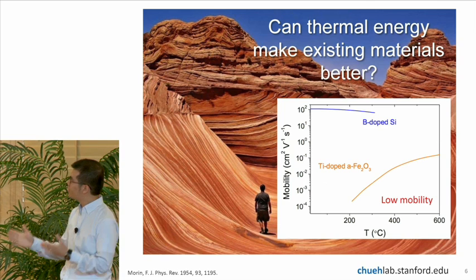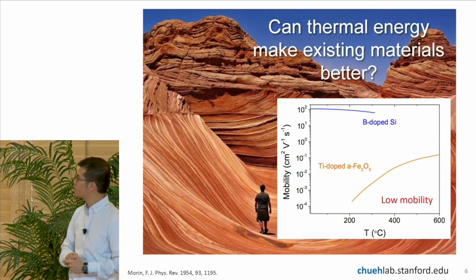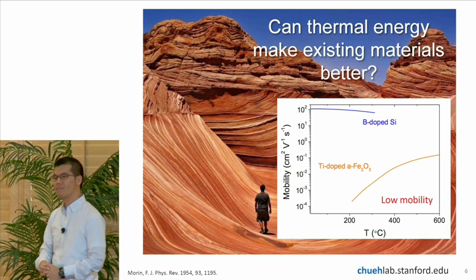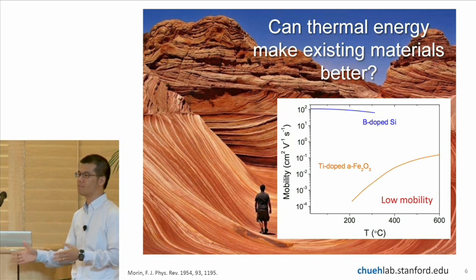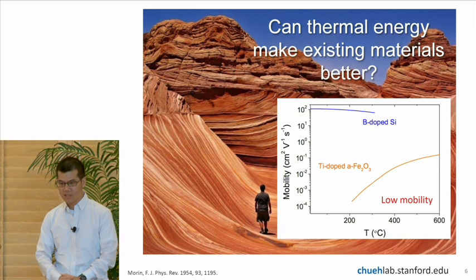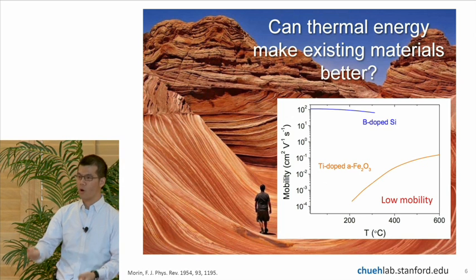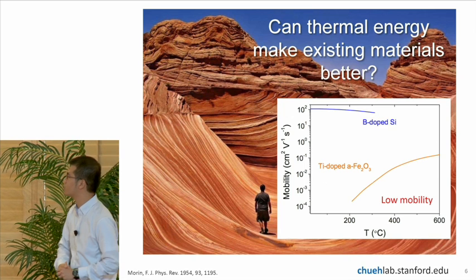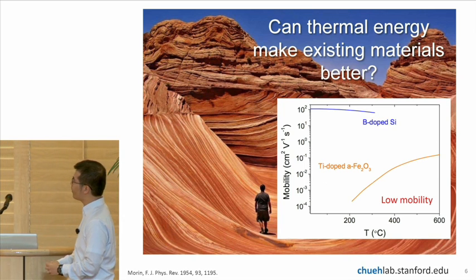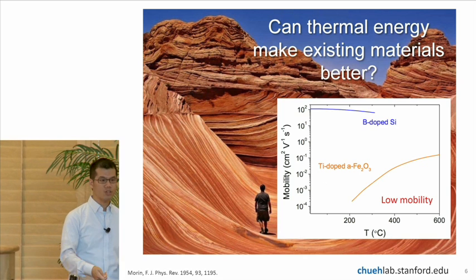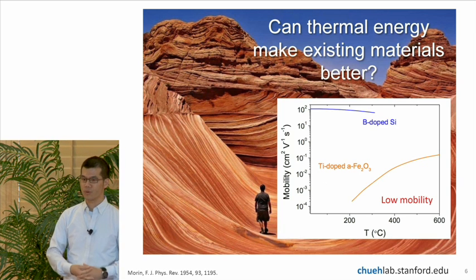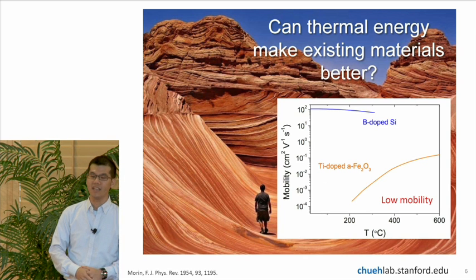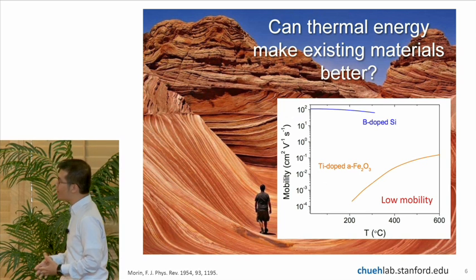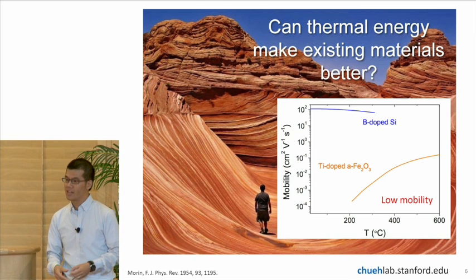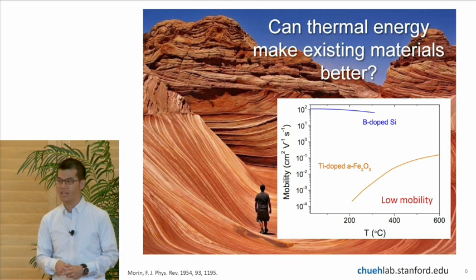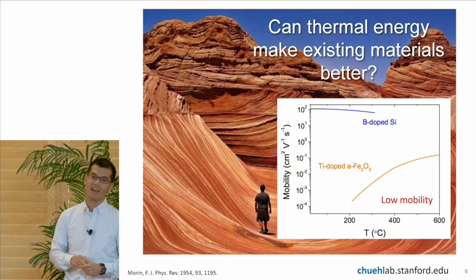The problem with materials like iron oxide, and another one I will talk about next, is they are not very good semiconductors. So if you consider any photovoltaic-based process, you have to be able to absorb sunlight, then you have to be able to generate electron hole pairs, and you have to be able to separate them, just like any other solar cell. The problem with a material like iron oxide is that the electrons and holes move very slowly in the material. So the possibility for them to come back and generate heat is fairly large. The reason why iron oxide is not a very good semiconductor is because the mobility of what we call the minority carrier, the electron in this case, is very, very low.